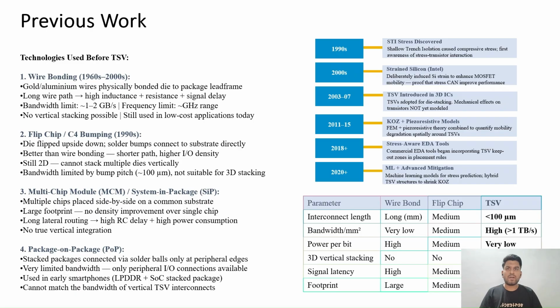Package on package allowed stacking of packages, but only peripheral solder balls were used for the connection, so bandwidth remained limited. The real breakthrough came with TSVs, which enable true 3D vertical integration with very short interconnect length, high bandwidth, low power per bit, and reduced latency. On the right side timeline, we see that stress effects were first noticed in the 1990s with shallow trench isolation. Later, strained silicon technology showed that stress can intentionally improve transistor performance. When TSVs were introduced in the early 2000s, mechanical effects were not initially considered. Over time, researchers began modeling TSV-induced stress, defining keep-out zones, and recently even using stress-aware EDA tools and machine learning for mitigation.